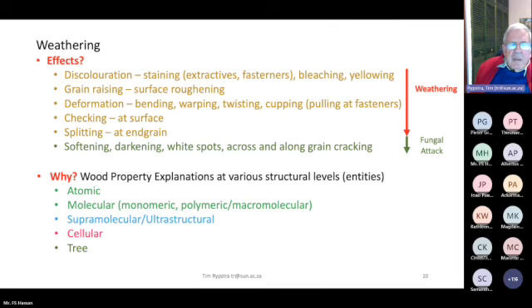It's followed by grain raising, which actually is surface roughening, and deformation, which can include bending, warping, twisting, and cupping, and that already is generating some forces which are pulling at the fasteners. Then, at a more advanced stage, you can get checking at the surface, and if it really is bad, then you can get splitting at the end grain.